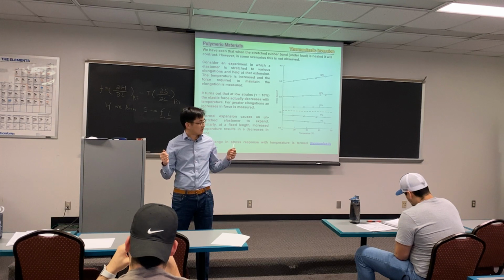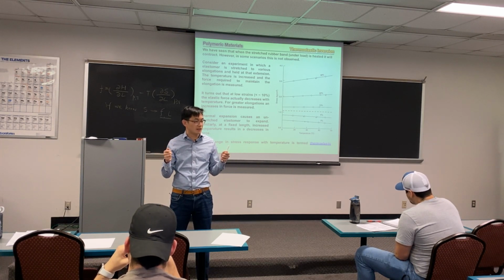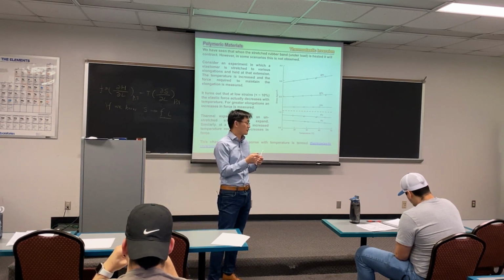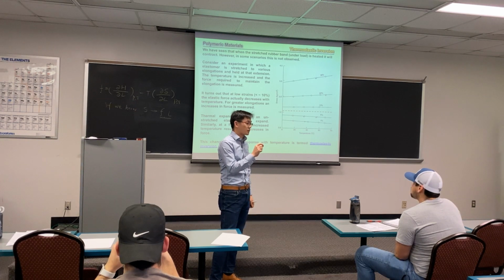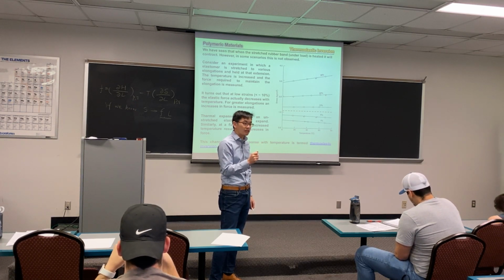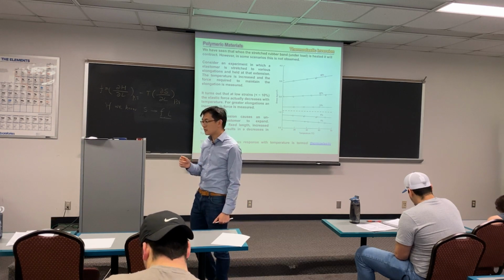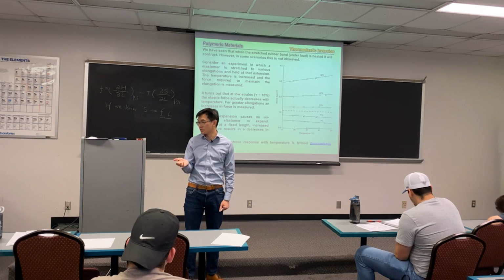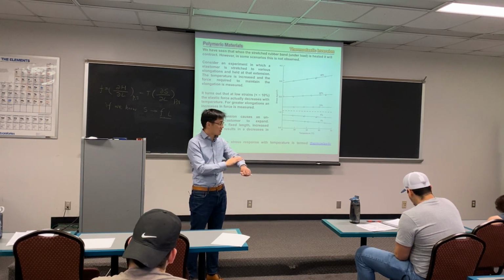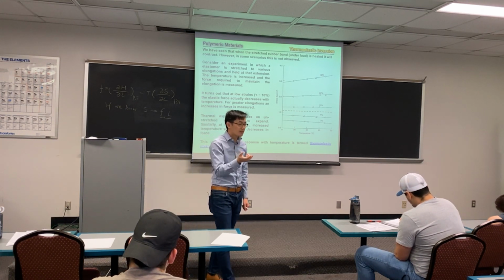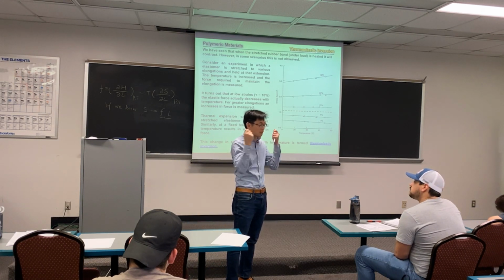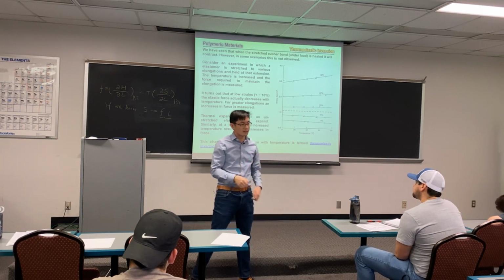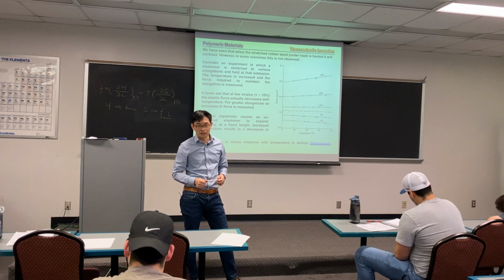And if you let it go, the rubber band in the stretched state will relax back, but at the same time it will take some heat from the environment. It's a tiny change in temperature, probably less than a degree, but if you put it against a sensitive part of your body, you can really sense the tiny temperature change. Not with your palm, but actually close to your lip. It's the most sensitive skin, and if you pull a rubber band back and forth, you can sense it going through the heat and cool cycle. Okay.